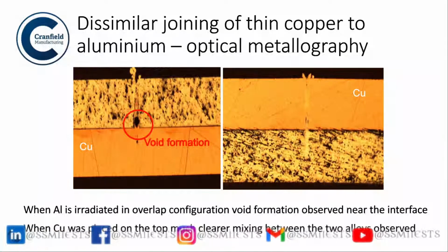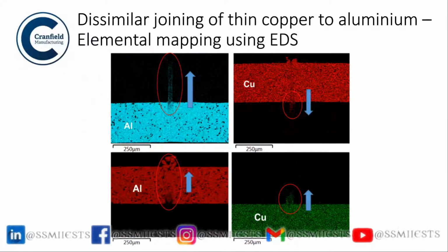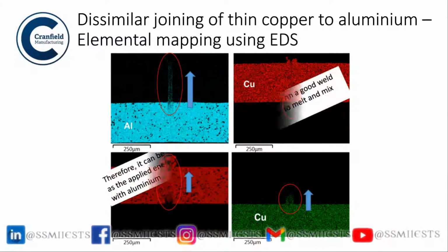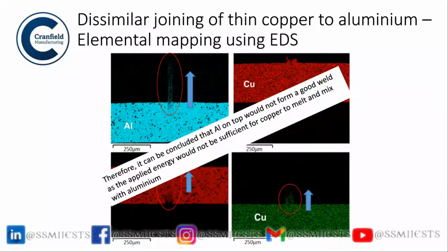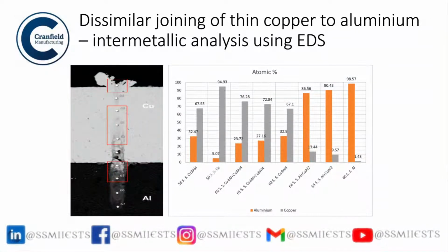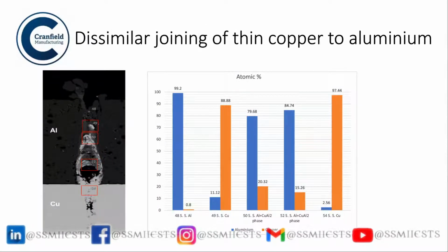You will see now from the EDS curves that when copper is on the top, it really gives you very good penetration of aluminium, and copper also penetrated significantly in the aluminium, whereas in the other case there was not much penetration of copper into the aluminium, and therefore the joint formation was not very strong, although it was not seen that much in the mechanical strength, but that was what was found from the EDS analysis. So these are some elemental maps through the joint, and as you can see here, when copper is on the top, in this part you have significant penetration of copper, which makes the joint very sound, whereas when aluminium is on the top, aluminium didn't penetrate at all into the copper, and that is the problem.